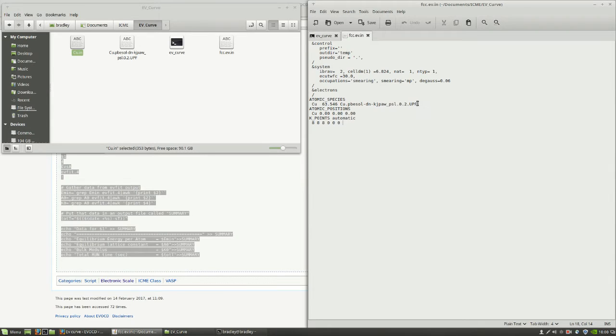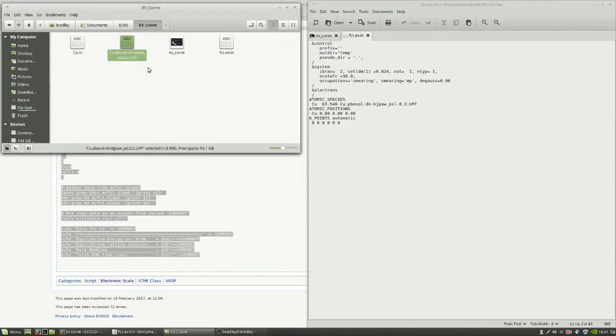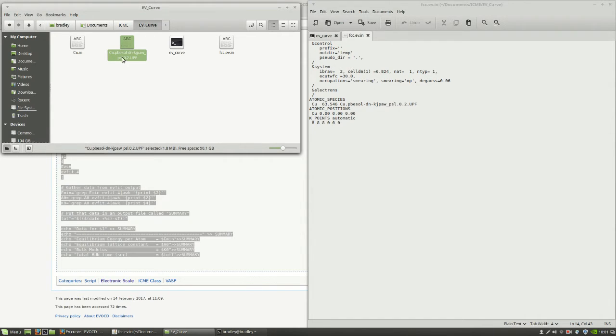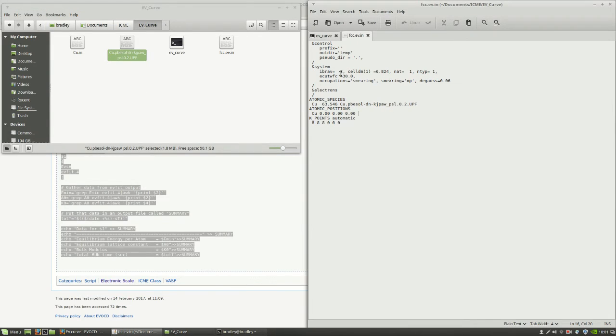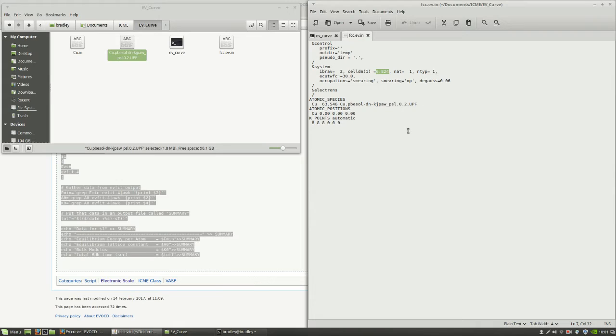First thing, let's make sure that we have the potential for the material that we want. You can see here I have specified this copper potential, and I have this copper potential in the folder where I'm going to be running these simulations. You'll want to pick a potential and a material and have that also in the same folder. I've also specified this to be an FCC lattice, which is good since that matches the name. One thing you do not need to worry about is this lattice parameter here. That lattice parameter will be replaced by the EV curve script so that it will iterate through all these lattice parameters that we want to calculate the energy of.